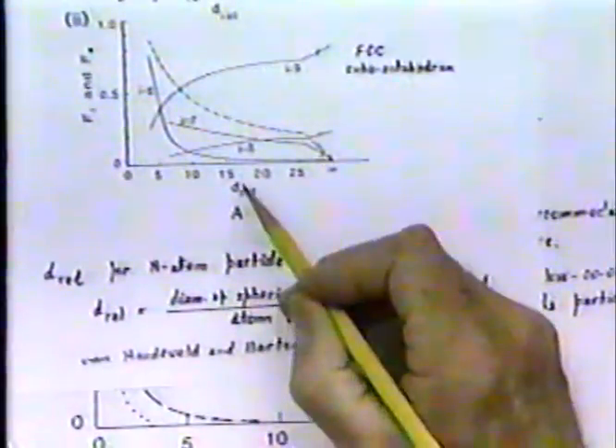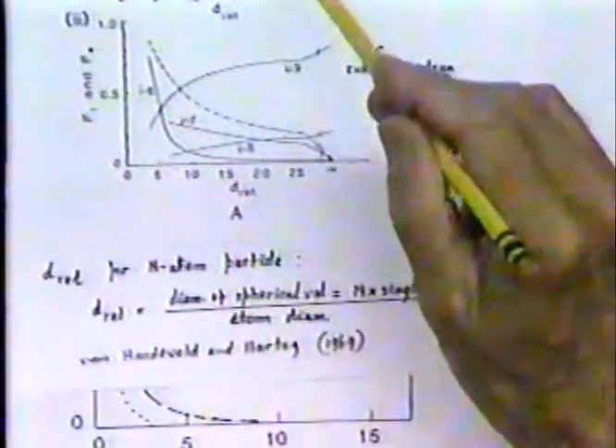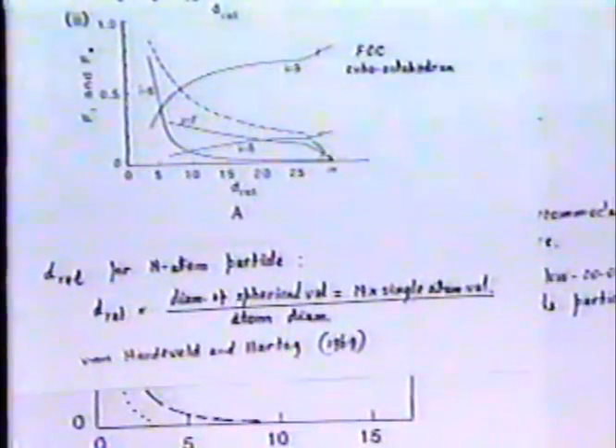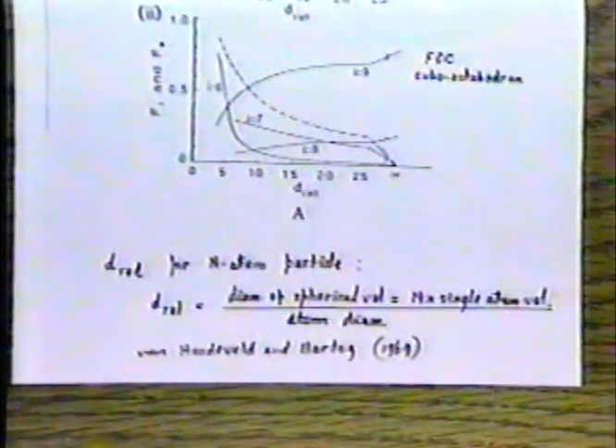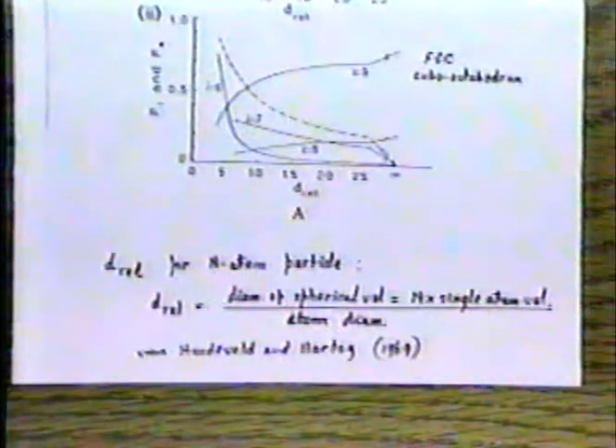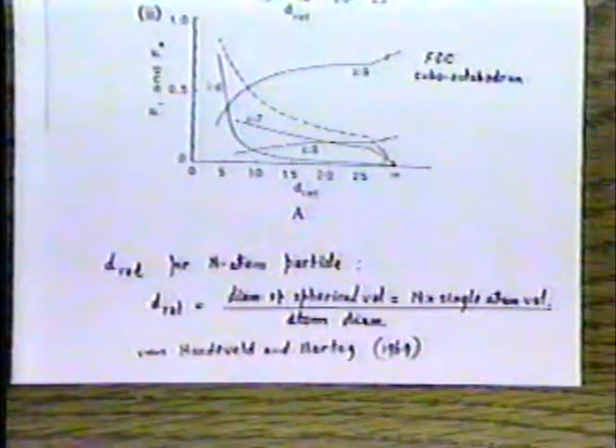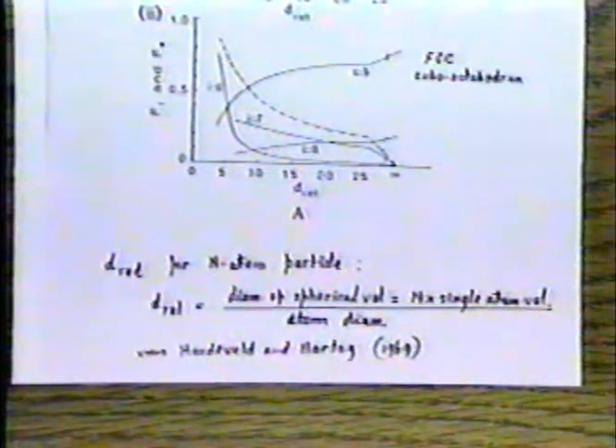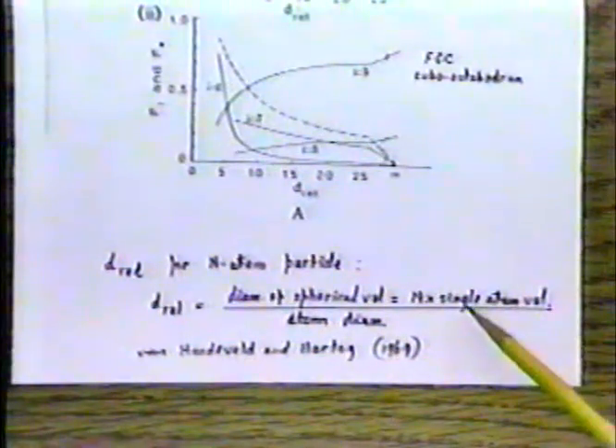D relative is a dimensionless parameter which is useful since it enables you to use these diagrams for any particular metal provided you choose the crystal habit correctly. And it's defined at the bottom of this sheet. It's the diameter of a spherical volume which equals n times the single atom volume, n being the number of atoms in the particle in question, divided by the atomic diameter. The atomic diameter, of course, is simply the nearest neighbor distance in the crystal. Since you're defining the size in terms of n, the single atom volume and the atomic diameter are in effect crystallographically determined parameters, and you can put numbers to them for any particular metal.